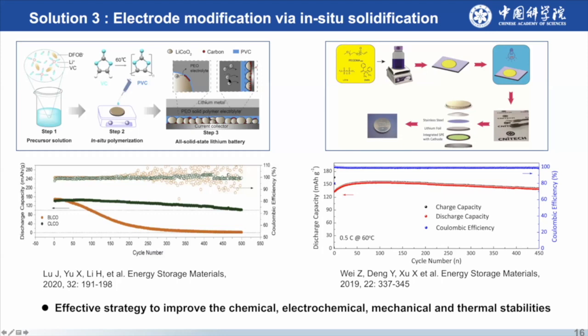You can get the result from here, you see, with the coating. So even this kind of battery can be cycled over 500 cycles. So this is very encouraging information for us that control the surface of the cathode is very important to extend the operation voltage range of the polymer, including polymer electrolyte or polymer binder.